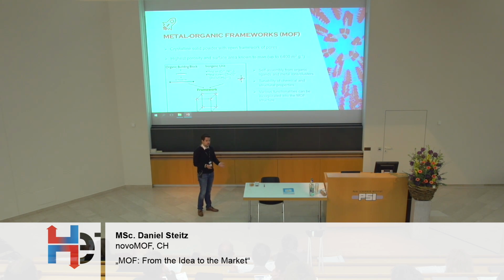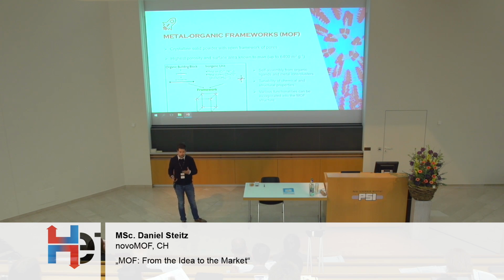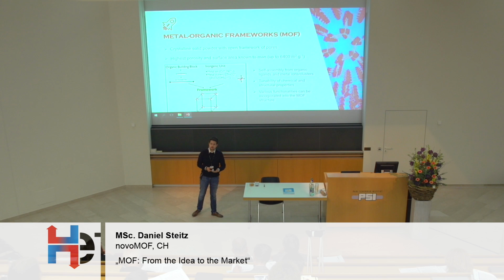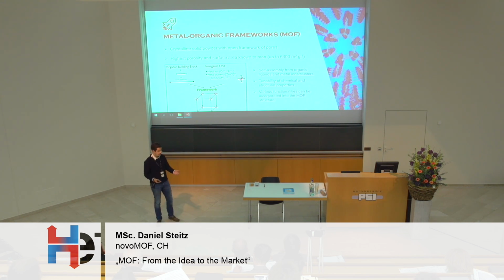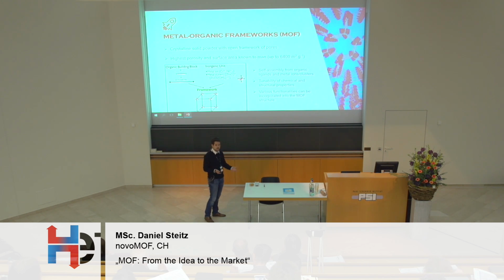And the great thing about these materials is, first of all, the tunability, because basically you can take any metal, any transition metal from copper to zirconium, but also aluminium and iron, for example, as a metal source, and you can vary the ligand size, so making the ligands longer, more aromatic rings, for example, to form larger or smaller pores. And with that, you get great chemical and structural properties. And additional to that, of course, you can also include functionalities. So you can functionalize the organic linkers and get with that, again, specific properties, for example, chemical behaviors.